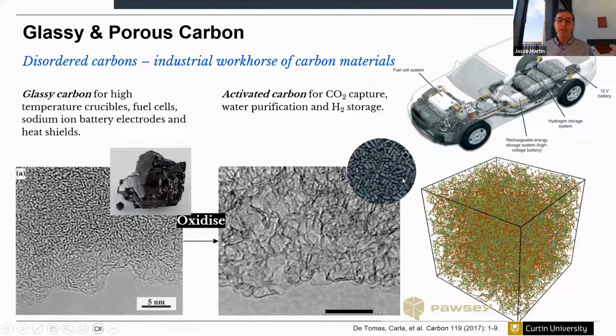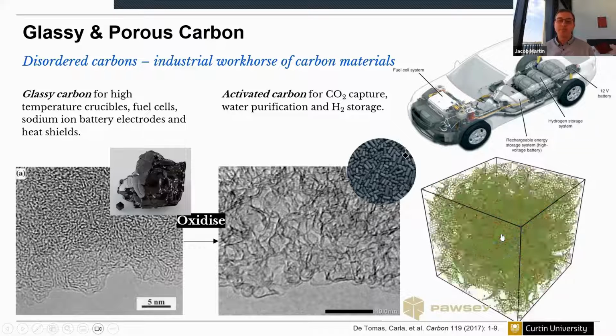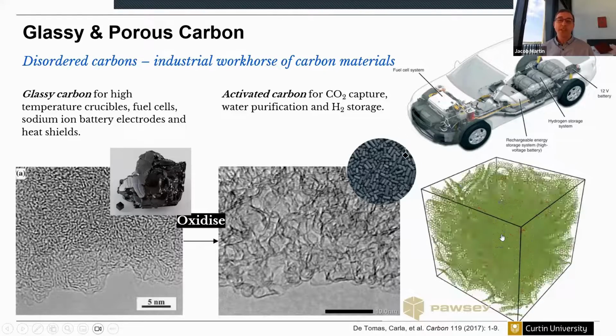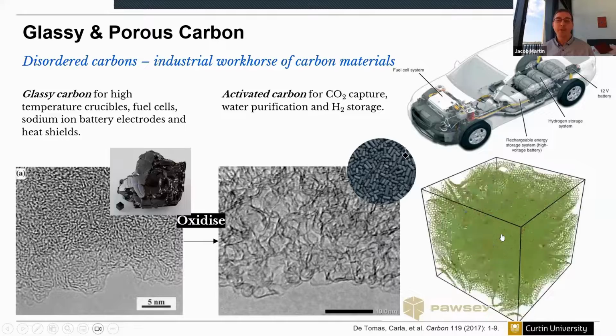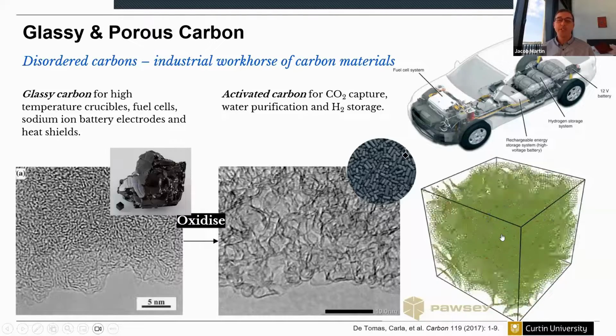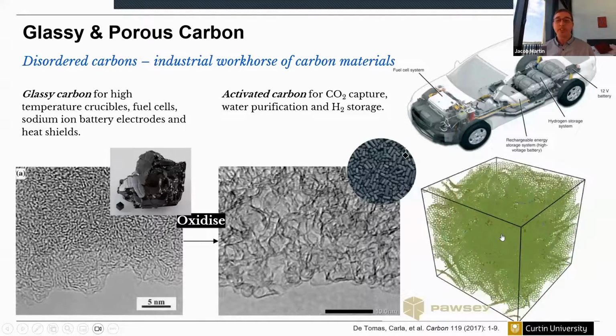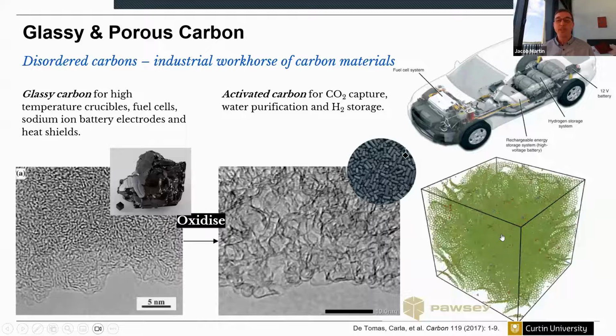And before I arrived in the group, Associate Professor Nigel Marks had spent a lot of time trying to develop incredibly accurate models of these carbons using molecular dynamic simulations. So here is a simulation showing an amorphous carbon that's annealed. And what you see is the self-assembly of a highly structured, complex network of graphene sheets in 3 dimensions. And after a lot of benchmarking and about 10 years of work, these models represent a highly accurate description of disordered carbons. They're able to capture all of the major features, both in the XRD and also the electron microscopy, all of the textures.